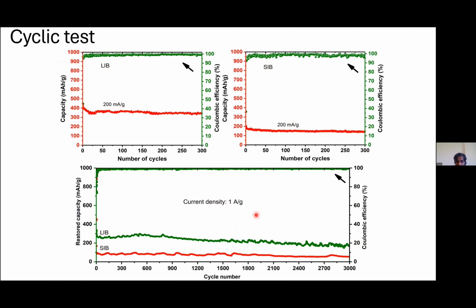And what about high current density charge discharging? This was done up to 3000 cycles, and it's very good as well, except a slight performance decay in the case of lithium ion battery, but not very much. Look at 3,000 cycles. If you assume the battery, whatever you are using in your cars or even wristwatches or your laptops, that you charge once in a day, that means 3,000 cycles is almost closer to 8 years and 2-3 months, right?